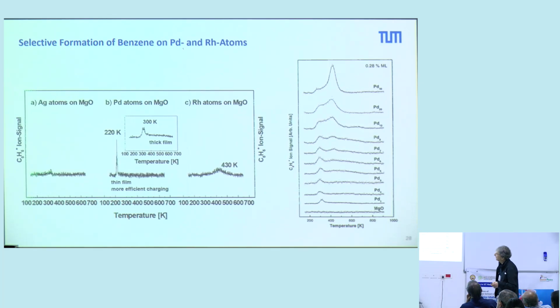You see silver on magnesium oxide, a very tiny reactivity. You have palladium on magnesium oxide. You have here a reaction at 220 K at low temperature. Here you have thin films. I will show you that the thin film has the influence that it charges the palladium, and this will be important. If you use a thick film, you change the reaction temperature. So the environment of these palladium atoms are important. Rhodium, you see production at 430 K.